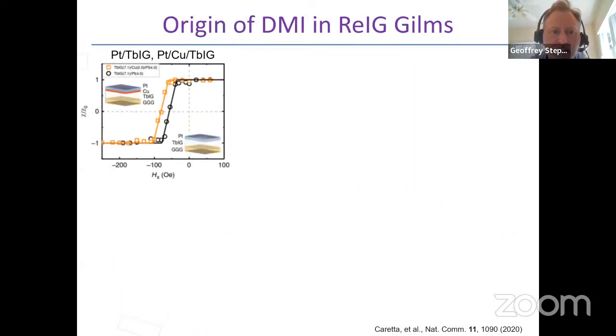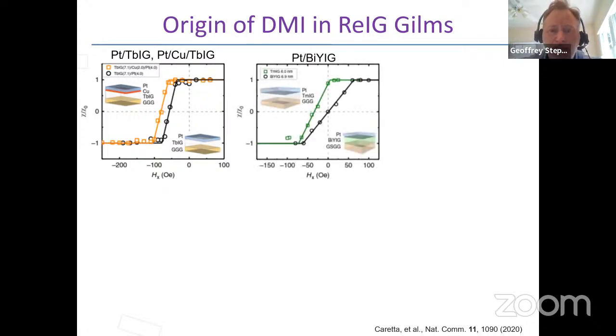We've looked at the roles of interfaces, and for platinum cobalt, it is the heavy metal, the platinum, and the spin orbit coupling that generates the DMI. What we found in these kinds of materials is that if you put a copper spacer between the platinum and the garnet, the DMI actually goes up. Whereas if you had a cobalt platinum interface and you did the same thing and put a copper spacer, the DMI would go down. And so that tends to suggest that it's not the metal that is imparting the DMI, or at least not the spin orbit coupling of the metal.